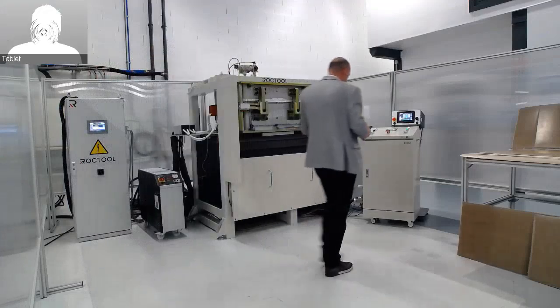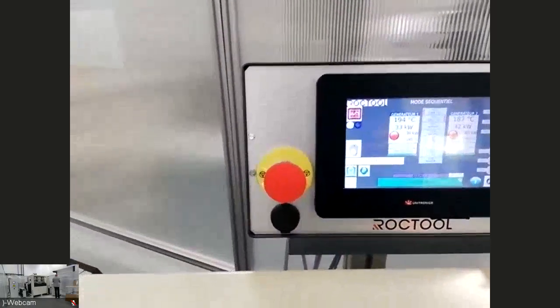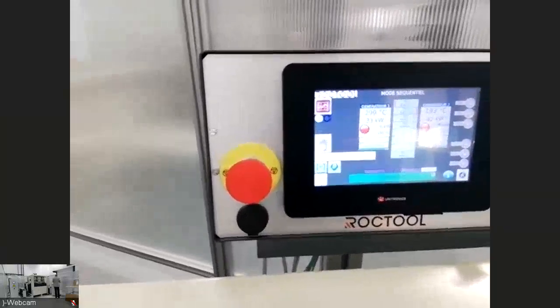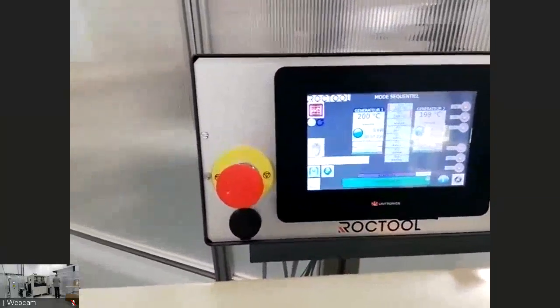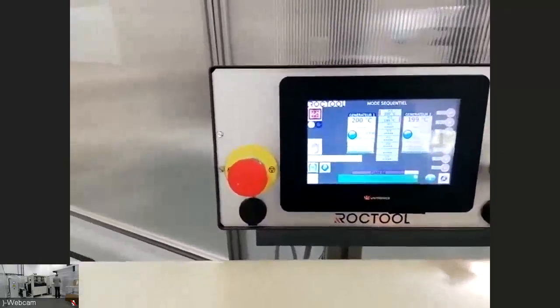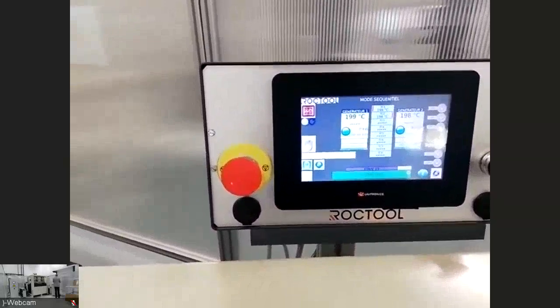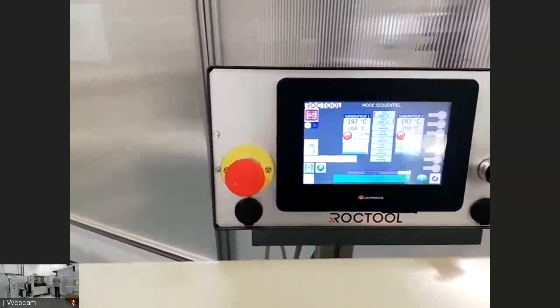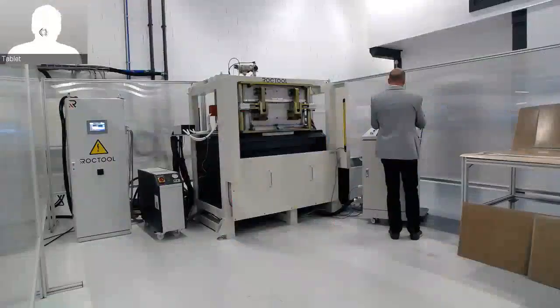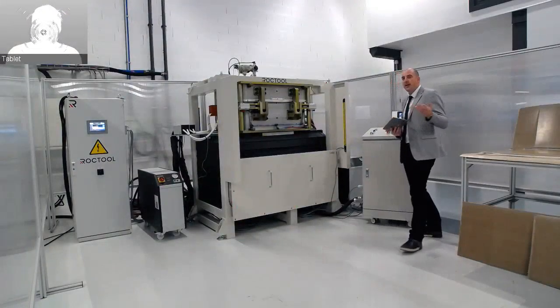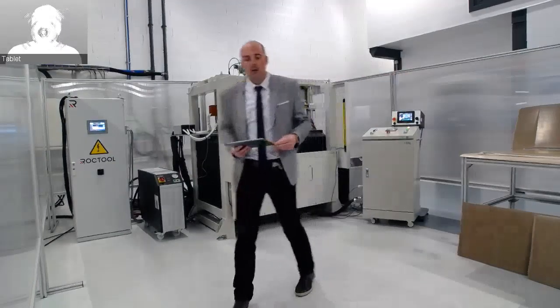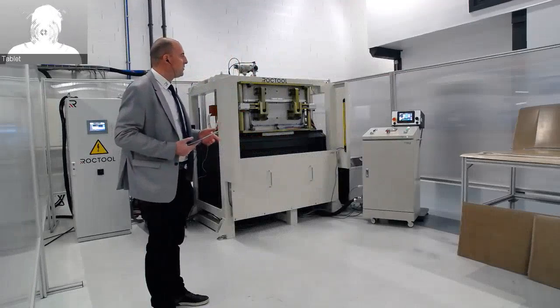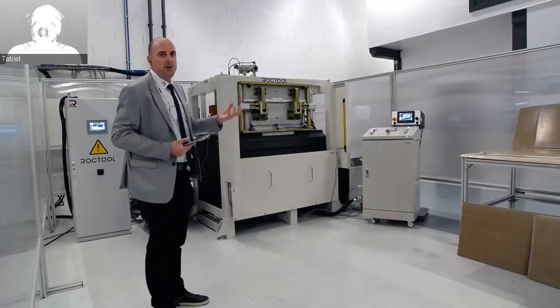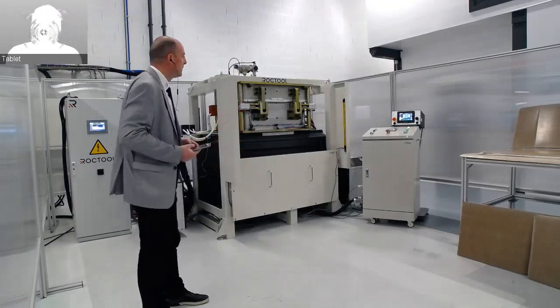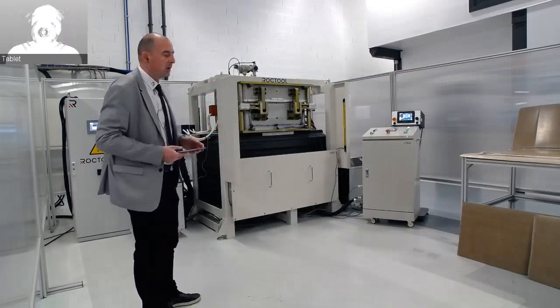So just also a quick view of the cycle. In this case we reach the 200 degrees in less than 1 minute and 20 seconds. We have a holding time around 1 minute because we use bio-based materials. And we use a 3-layer with this material, with the Bcomp material. So we need time to have heat diffusion through the 3-layer of material to have a good impregnation and good consolidation of the material.